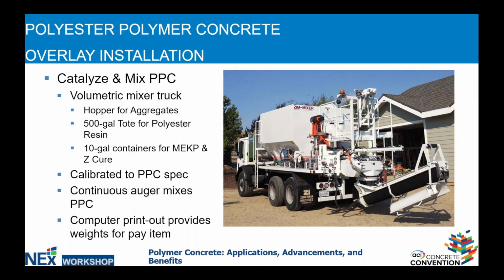It's not always necessary to accelerate. Sometimes our substrate bridge decks are warm enough to move forward without the need for the accelerator. The truck itself is calibrated for the PPC spec, and most specs, DOTs that are very fond of this type of technology, are calling for a typical 12% resin content in that overall blend of resin, aggregates, etc.